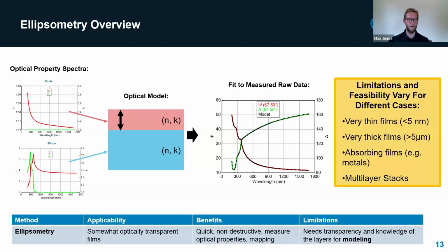And so in the base case where we know the optical properties and we just want thickness, we just simulate a whole bunch of different thicknesses. We run a fit regression on that. And once the simulated data, so on the raw data graph, the dotted black line, once that matches up to the raw data that we measured, whatever the corresponding thickness was that was required to get that, we take that to be the correct thickness.